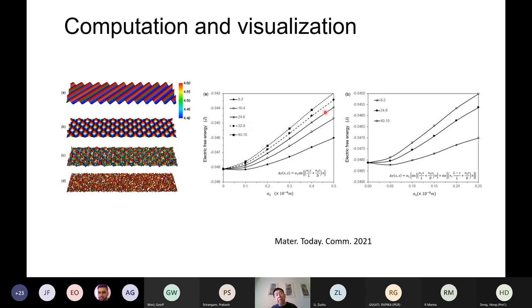So we calculated, according to our theory, that the electric current can change the surface roughness, mainly making the surface smoother. So in steel making, if you have a much smoother mold flux, then the steel surface property will be better. So we published a theory and experiment; now, in other consideration.